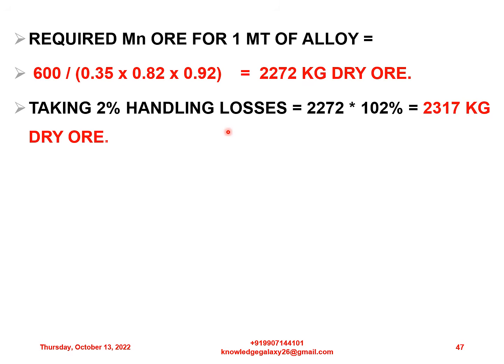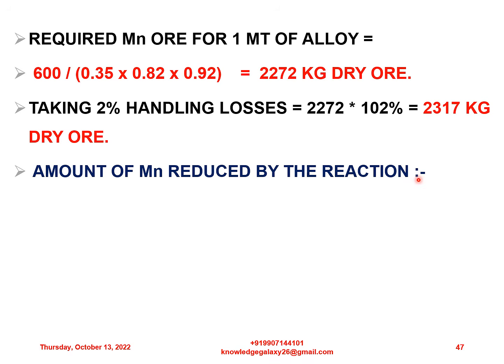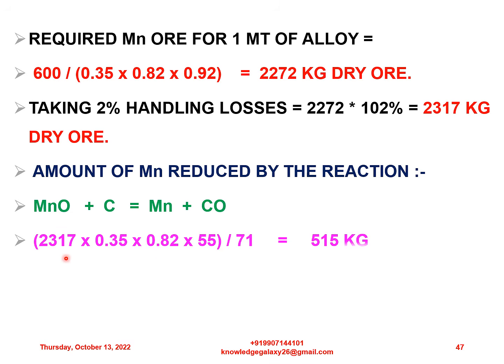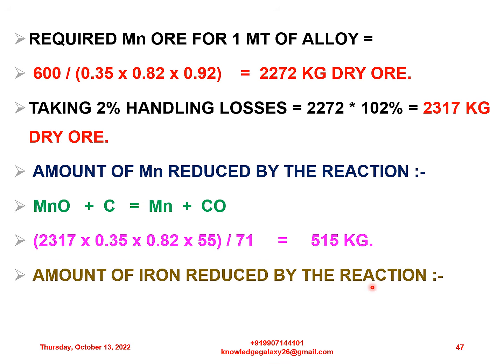And now taking 2% handling losses, it comes to 2272 into 102%, that is with 2% handling losses, 2317 kg of dry ore. Now the amount of manganese reduced by the reaction MnO plus C is equal to Mn plus CO. It gives 2317 into 0.35 into 0.82 into 55 whole divided by 71 is equal to 515 kg. 55 is the atomic weight of manganese and 71 is the molecular weight of MnO, that is manganese plus oxygen. Next is the amount of iron reduced by the reaction FeO plus C is equal to Fe plus CO.